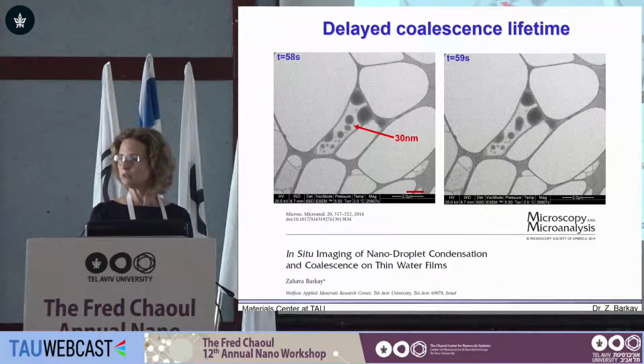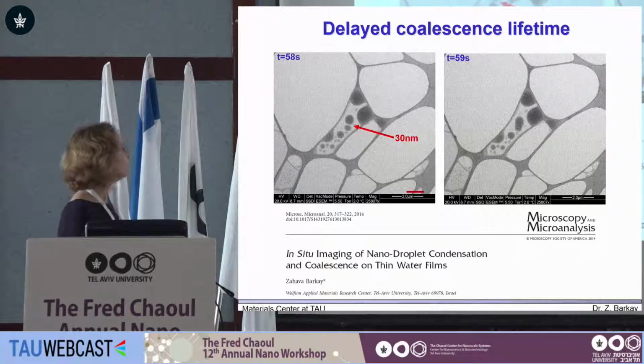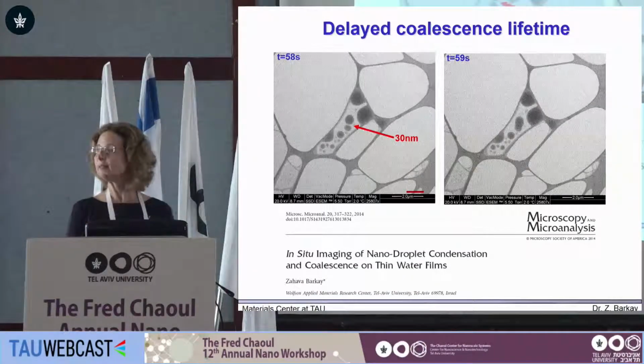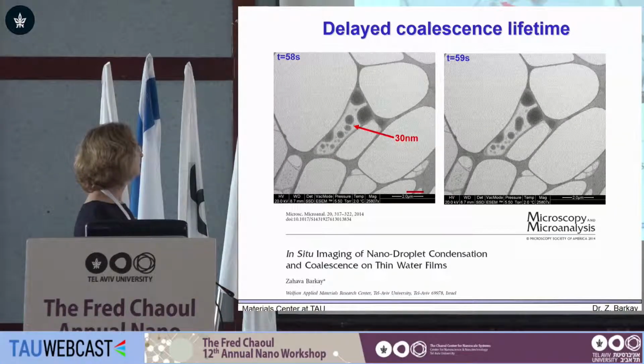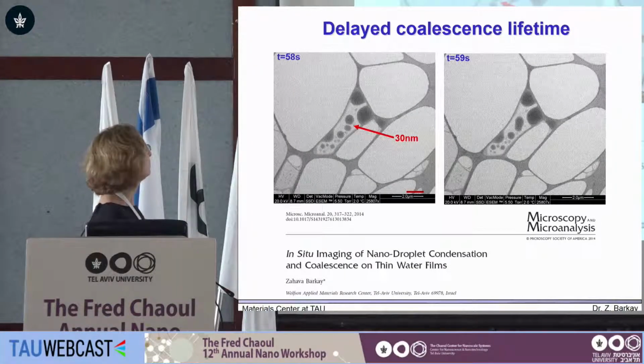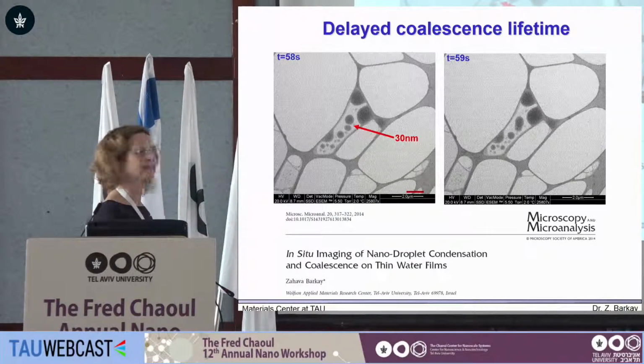In addition to this long lifetime, we have also long coalescence, and we can see here again - this was taken from a movie. This is at 58 seconds. We see here 30 nanometer spacing, and flat facets as should occur, but very long lifetime, and then some coalescence which occurs within 1 second, but still the liquid is not very well organized.